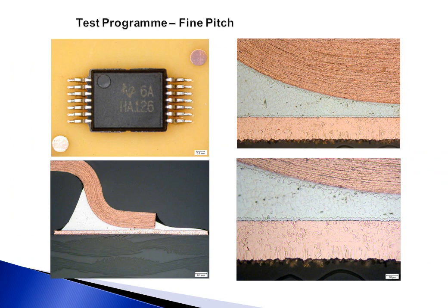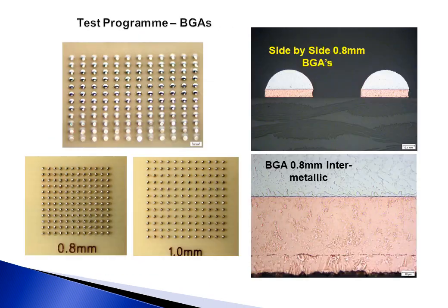Tried fine pitch and again got very good joints. BGAs, no problem at all. Went down to 0.8 millimeter BGAs, but again we had them sectioned and you could see the intermetallics there that are quite good.